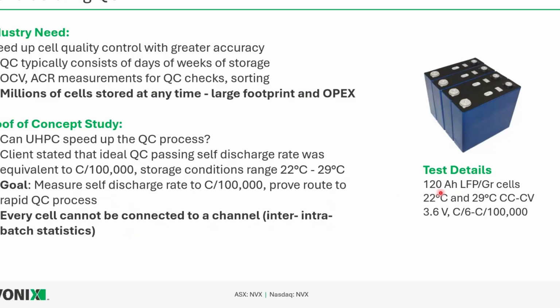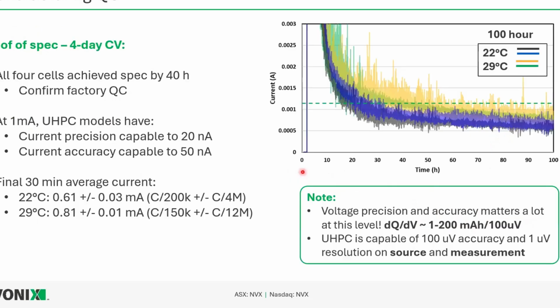We did these tests on these 120 amp hour LFP graphite cells and operated at the endpoints of what was considered to be that storage range, and did 3.6 volt CCCV testing from C over 6 on a 20 amp UHPC circuit, and then tried to test down to C over 100,000. For this proof of concept, a 4-day CV, so over 100 hours, we put these cells on test and did a constant voltage hold at 3.6 volts.